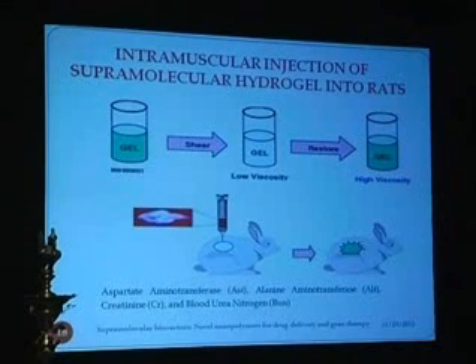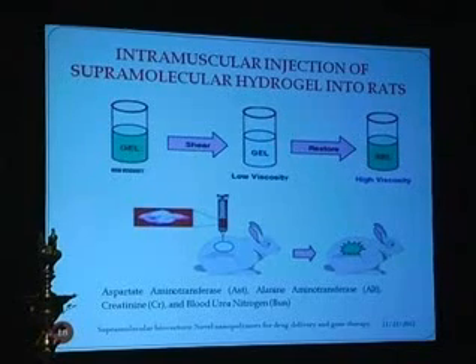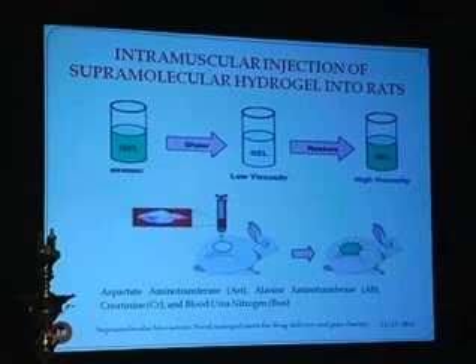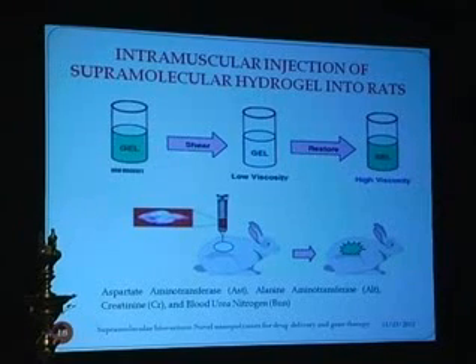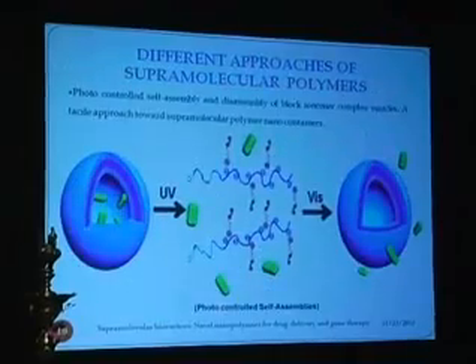Another is intramuscular injection of supramolecular hydrogels. First of all, you convert high viscosity gels, that is hydrogels, by applying shear. It is converted into low viscous. If you let it rest for some period of time, then again the viscosity increases. So it is the beauty of the hydrogels. Because of the increasing viscosity, there is a very good sustained action.